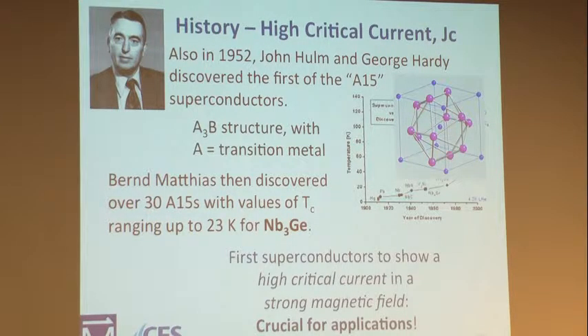This made it a better superconductor because it was higher TC and higher JC, but it was also hard to work with. That's because it's a compound, and that crystal structure became imperative to it. So if you actually messed up the crystal structure, ground this thing up, hit it with ions down the road here, in the same building here, you would actually destroy the superconductivity or lower it. The crystal structure being sound was very, very important.